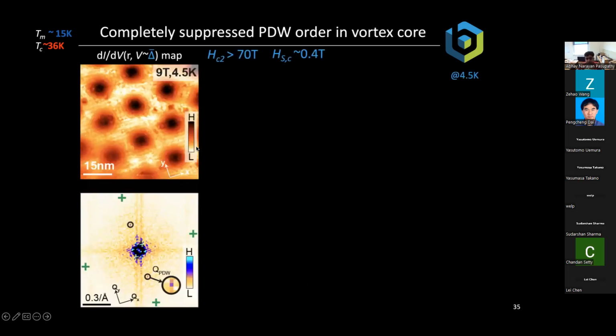Now, the other thing that we'd like to really show is that this phenomenon is related to superconductivity. And in order to do this, what we do is we apply a magnetic field. And a magnetic field creates superconducting vortices. And here we apply a magnetic field of 9 Tesla. And when we apply this 9 Tesla magnetic field, you can see all the superconducting vortices in the sample very, very nicely. And inside a superconducting vortex, the superconducting order parameter is suppressed for the uniform superconductor.